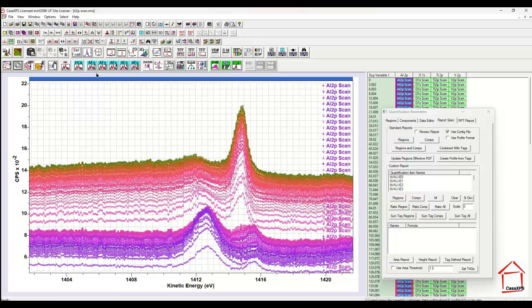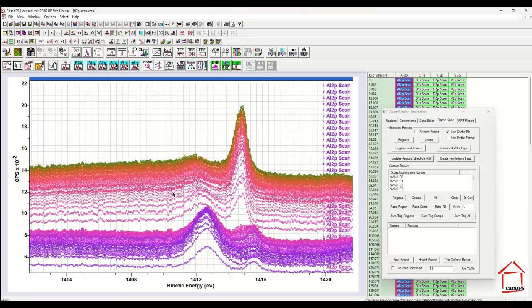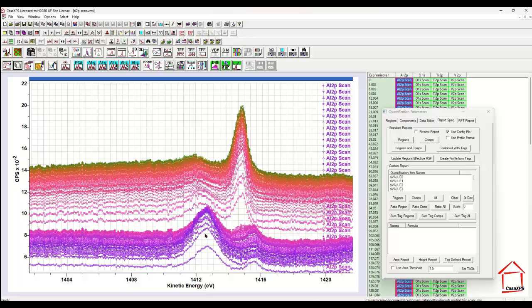And this is quite useful because not only does it show us the improved signal to noise, but we can also see that perhaps the region originally chosen was too broad and didn't include enough of the signal and exclude enough of the background. And that's clearer because we see now the oxide and the metal peaks all nicely defined.